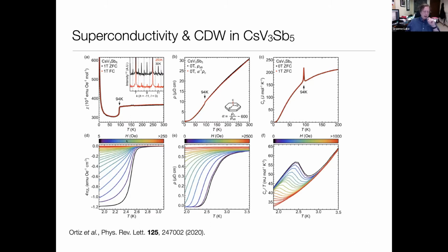So there's a charge density wave at about 94 Kelvin in this material, which shows up in all these bulk measurements. But then, interestingly enough, if you cool down to even lower temperatures, you end up with a superconductor as well. Here's the resistivity: you go from a finite resistance state down to a zero resistance state at around 2.5 Kelvin. You see that in the magnetic susceptibility, where you get full flux expulsion, indicating a bulk superconductor. You also see a sharp lambda-like anomaly in the specific heat, which you can then depress with a magnetic field as you move through the critical fields. So again, you have a superconducting state emerging out of a metallic system which has a charge density wave in it as well.